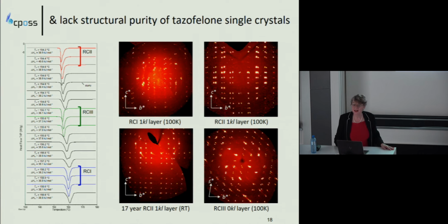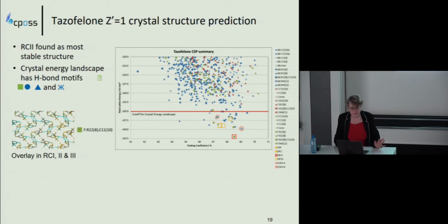Try to get our energetics to test our energies. Oops, even by doing the measurements on single crystals, they were getting variations in melting points and heat of sublimation, which eventually, by looking at the raw diffraction data, it's streaky. There's disorder in it. Okay, disorder. So how did we do in CSP?